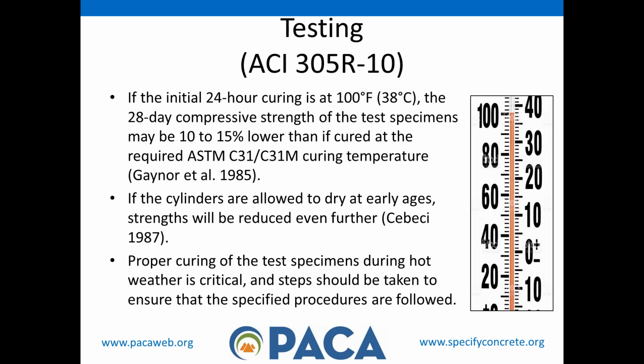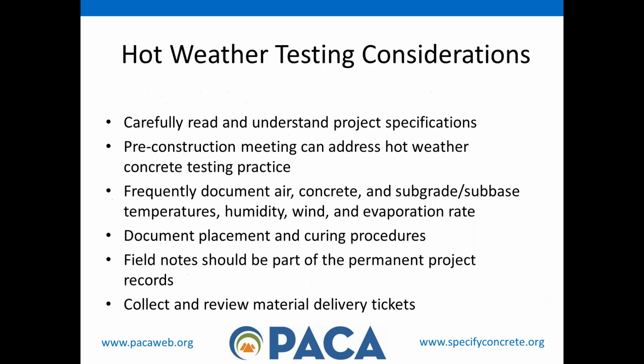So, looking into ACI 305R, it reiterated that if the initial curing is at 100 degrees, the 28-day compressive strength of the test specimens may be up to 10 to 15% lower than if cured at the required temperature. If cylinders are allowed to dry at early ages, strengths will be reduced even further. So proper curing of the test specimens during hot weather is critical, and steps should be taken to ensure that the specified procedures are followed.